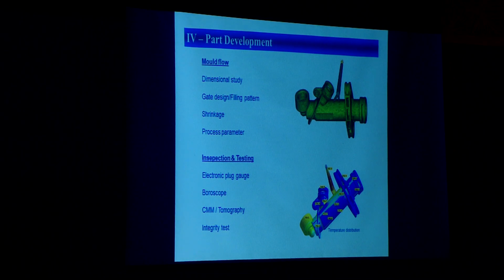Then we started with the part development. First, we went through the mold flow analysis. We were able to do the dimensional study. We identified which is the best gate design for this part. How would the filling pattern vary if any other alternate gate designs were provided? The shrinkage, material shrinkage and the part shrinkage. Process parameters, what would be the best process parameters that would be required to mold this part?